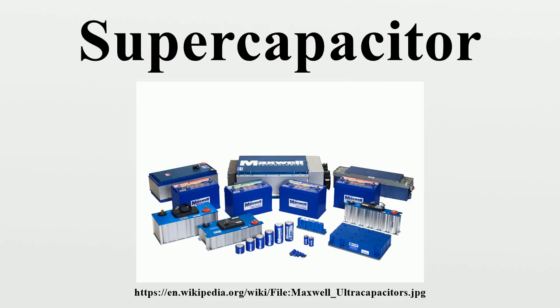Supercapacitors do not use the conventional solid dielectric of ordinary capacitors. They use electrostatic double-layer capacitance or electrochemical pseudo-capacitance or a combination of both instead. Electrostatic double-layer capacitors use carbon electrodes or derivatives with much higher electrostatic double-layer capacitance than electrochemical pseudo-capacitance, achieving separation of charge in a Helmholtz double layer at the interface between the surface of a conductive electrode and an electrolyte.